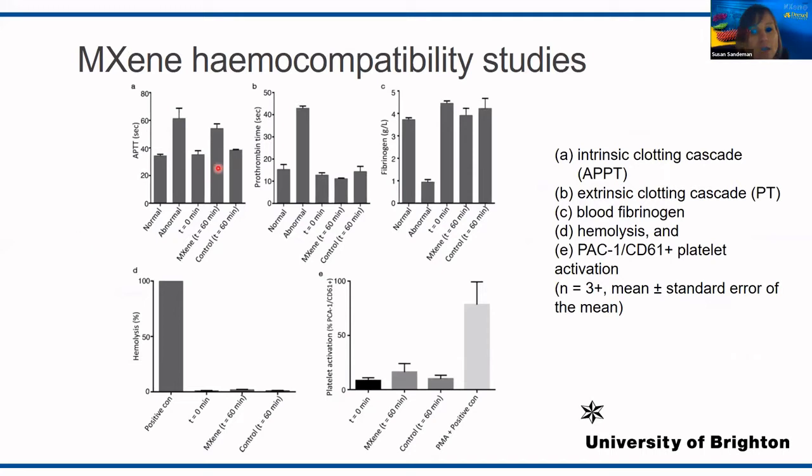We looked at the intrinsic clotting cascade, so does MXene induce coagulation? We looked at whether it takes out clotting factors from the blood, whether it causes hemolysis, and whether there is platelet activation. And we found that there was a slight rise in the intrinsic clotting cascade. There was a slight increase in clotting time, but there was no significant impact on any of these factors